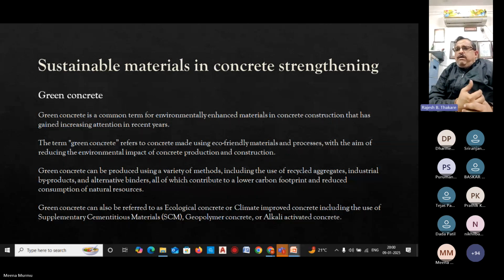So silica fume is a byproduct of silicon and ferrosilicon alloy production, which can also be used as SCM in concrete. Metakaolin is basically generated from kaolin rocks, and it is to be powdered in controlled condition. So that can also be used as SCM in concrete. Now GGBFS, that is ground granulated blast furnace slag, is a byproduct of iron and steel production, and these are industries in vast capacity in Chhattisgarh. So we can use this GGBS, which can be ground into fine product and used as cementitious material in concrete mixture.